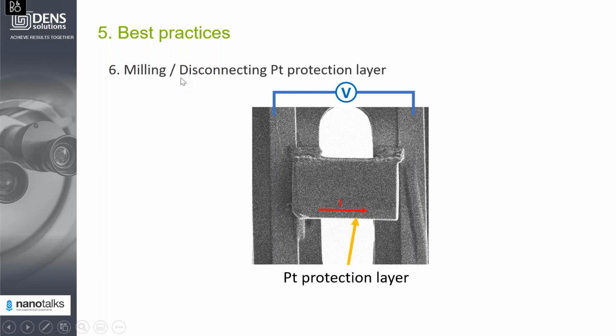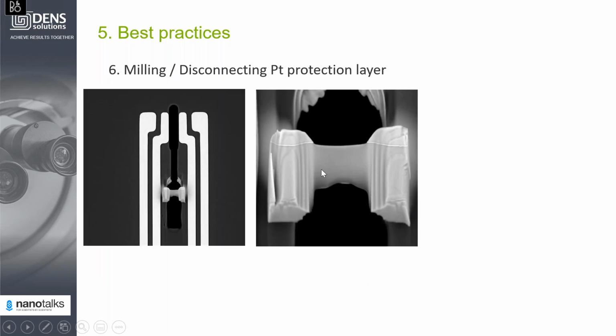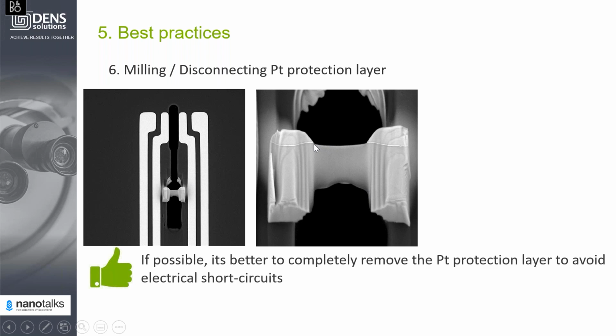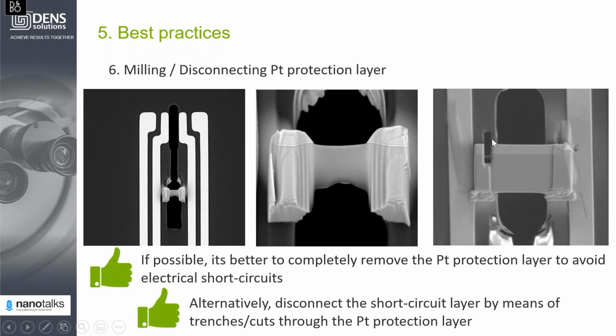So how to avoid, again, short circuit due to the platinum protection layer? One way to do this is to mill completely away the platinum, if it's possible. In this case, you will not have any issues with the platinum short circuit. In case your sample is positioned too close to the surface, so you cannot remove the platinum completely, what you can do is make cuts through the platinum layer just to disconnect the platinum protection layer.